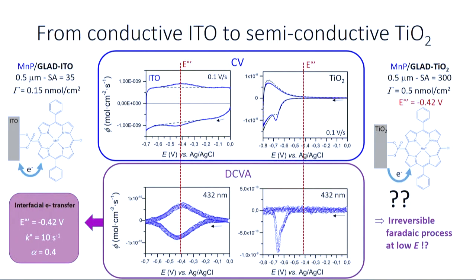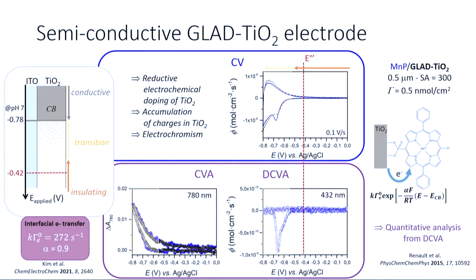And to understand this, we have to come back to what titanium dioxide is as a semiconductive electrode. It is characterized by a specific band distribution. You can indeed reach a conduction band, but this conduction band is at quite a low potential in aqueous electrolytes, meaning that over the largest part of the potential window in water, titanium dioxide is electronically insulating. And if it's electronically insulating, it cannot transfer electrons to an immobilized redox probe. So there is no way that you can reduce or reoxidize the manganese porphyrin at this specific potential, which lies, for example, here, if I compare to the band structure of titanium dioxide.